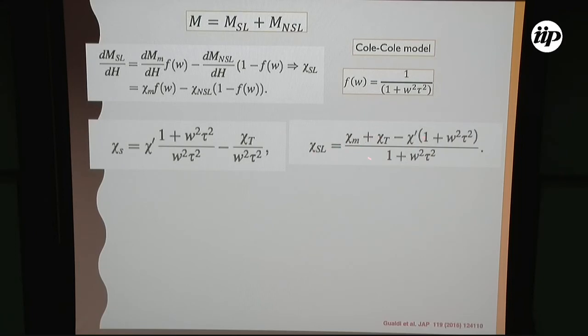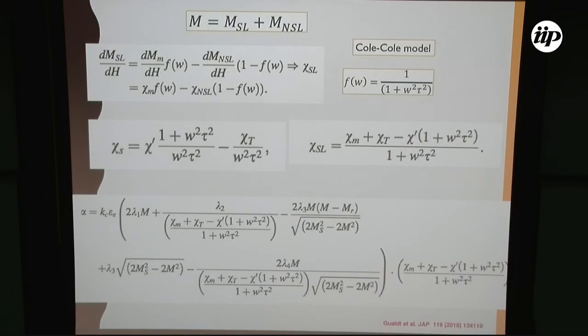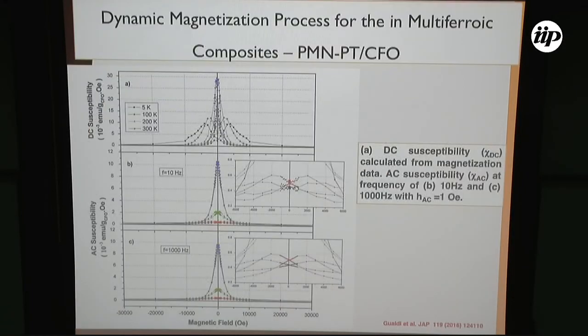It depends on the isothermal susceptibilities, the direction of deviation of magnetization as a function of field, and chi prime. Chi prime is the real component of the AC susceptibility. It depends on the frequency. So the magnetoelectric susceptibility is calculated using this expression proposed for composites, and my proposal for this susceptibility takes this form to describe this effect.